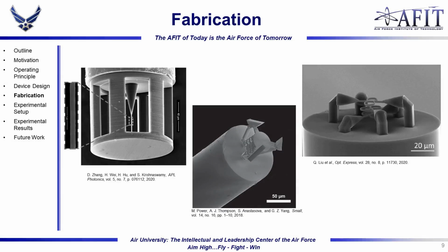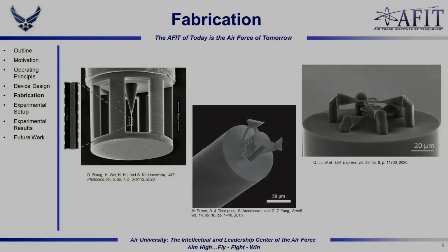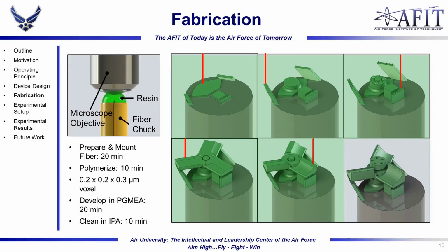This technique has already been demonstrated to create some really amazing devices on optical fiber tips, some examples of which are included here. Specifically, we mounted our fiber into a side-loading fiber chuck and loaded it into our two-photon polymerization system, the Nanoscribe Photonic Professional GT. This mounting process took about 20 minutes. Writing the device took about 10 minutes. You can see some of the layers as it was built up from the face of the fiber. You can see our voxel size there, that is in microns.